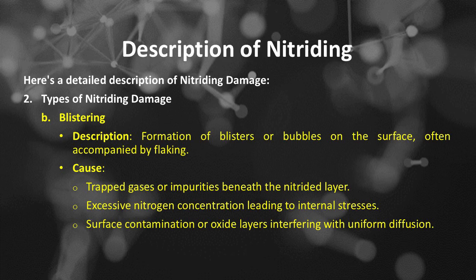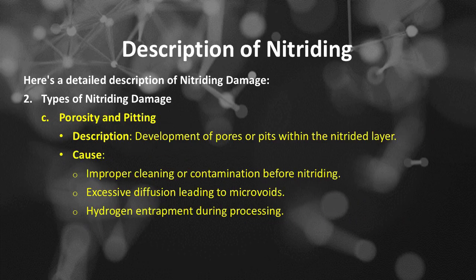Types of nitriding damage. B, blistering, described as formation of blisters or bubbles on the surface, often accompanied by flaking. Causes of blistering include trapped gases or impurities beneath the nitride layer, excessive nitrogen concentration leading to internal stresses, and surface contamination or oxide layers interfering with uniform diffusion. C, porosity and pitting, described as development of pores or pits within the nitride layer. Causes include improper cleaning or contamination before nitriding, excessive diffusion leading to microvoids, and hydrogen entrapment during processing.